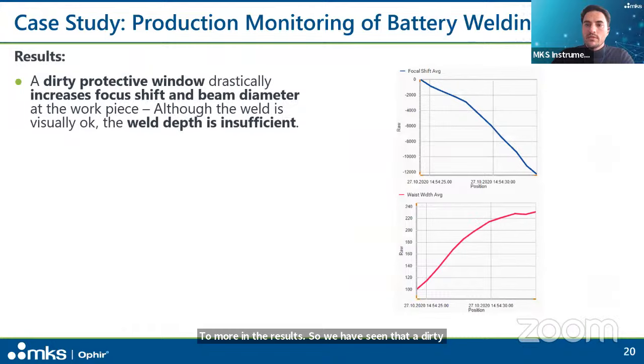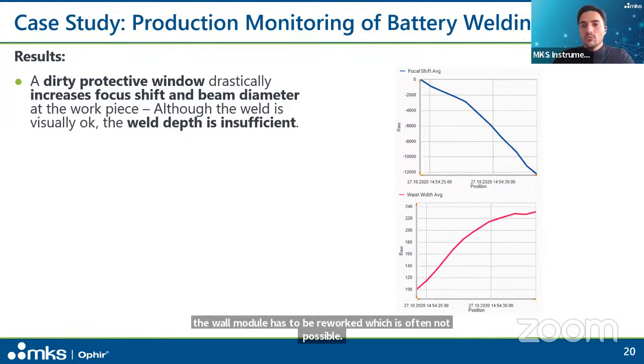So more on the results. We have seen that a dirty protective window increased the focus shift. This is the blue curve here, which automatically increased the focus diameter, the red curve here. And even if the weld visually looks okay, as I told you, the weld depth is insufficient and we have a bad electrical connection. That means the whole module has to be reworked, which is often not possible. So it has to be scrapped, which is quite expensive.